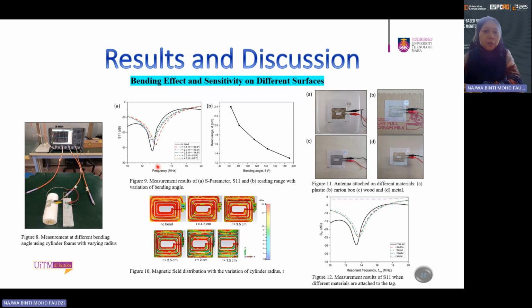Only when the cylinder foam is 1.5 centimeter, which is equal to 190 degrees of bending, the resonant frequency is shifted slightly to higher frequency, approximately 1 megahertz, but it is still within the acceptable range. But as we can see from the reading range here, as the bending angle is increased, the tag reading range is reduced from 2.4 centimeter to 1.3 centimeter when the bending angle is increased from approximately 60 to 190 degrees.